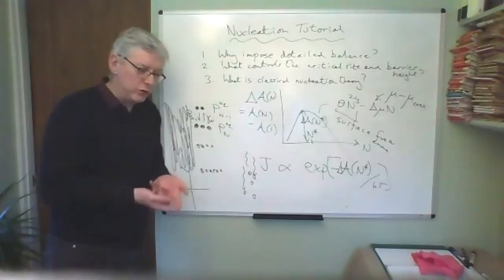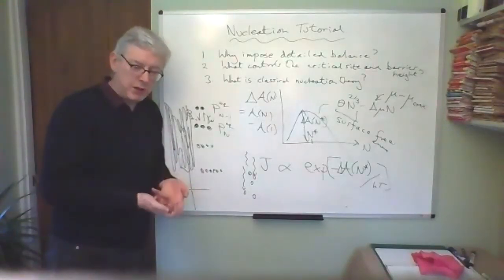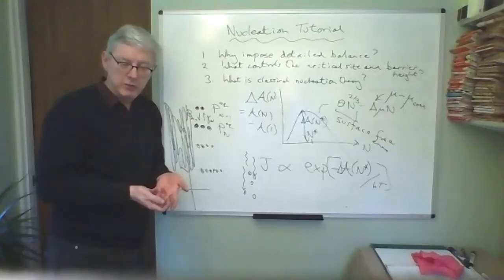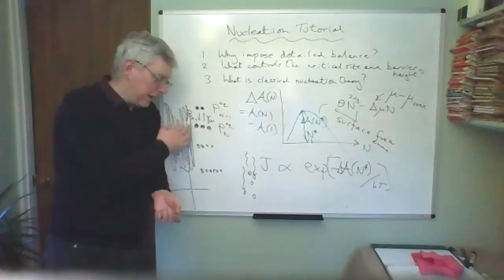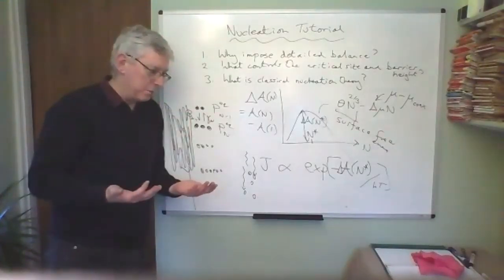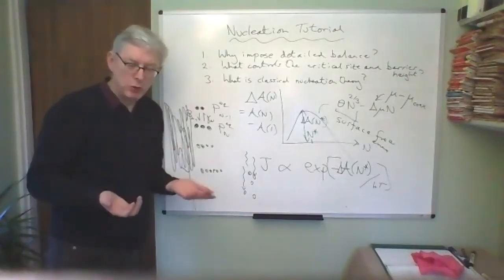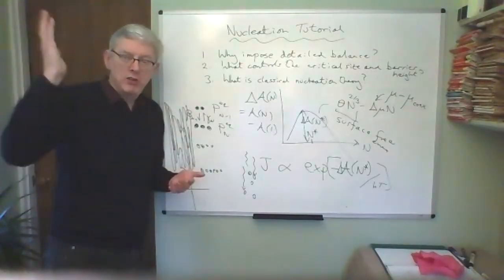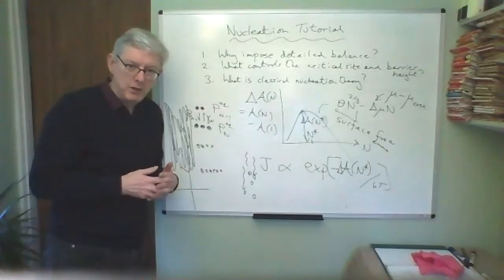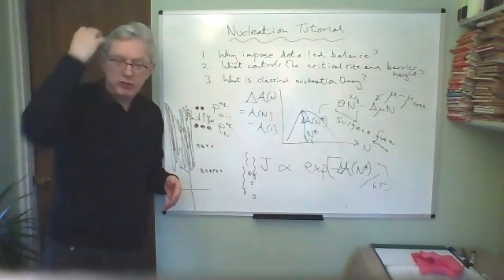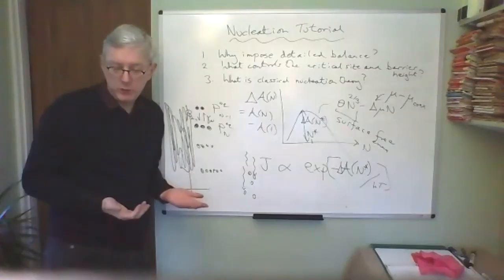And then we extrapolate from detailed balance conditions to out of balance by a bold step of saying all the growth rates increase in proportion to the relative humidity. So if it's 200% humid outside, then all the growth rates are double what they would be in coexistence.